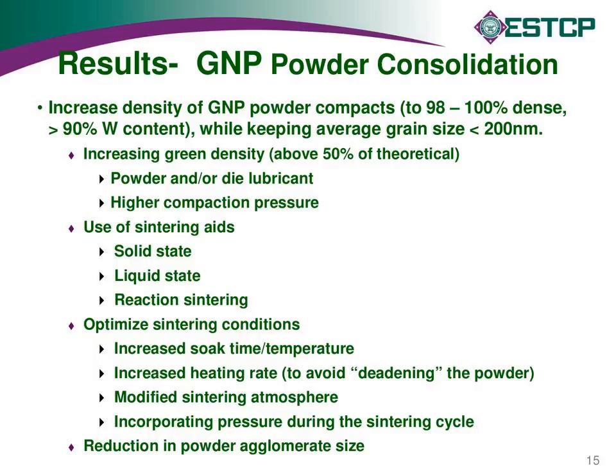Now ARL also worked with the powder quite a bit, and they have a very nice system for breaking up the agglomerate size, so they also did some work on agglomerate size. And I think ultimately the process that produced the large pieces for ballistics testing was run through the process to reduce the agglomerate size and sintered at ARL.